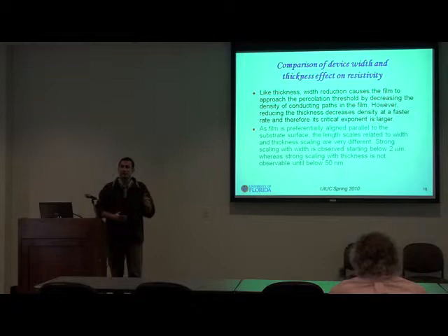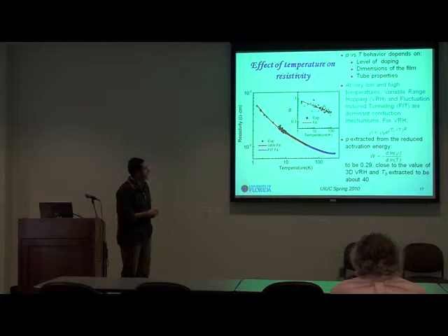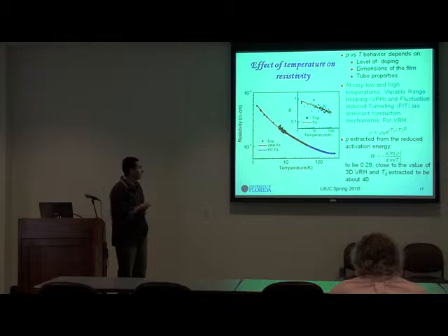The other thing we studied was that we said, okay, let's now decrease the temperature, from 300K to 4K, or even lower in some cases, 1.2K. This is one of those cases. What we notice is that, first of all, this dependence shows a strong increase in resistivity. It's actually falling in the regime between weak localization and strong localization.